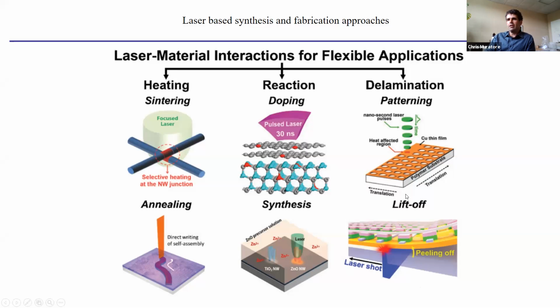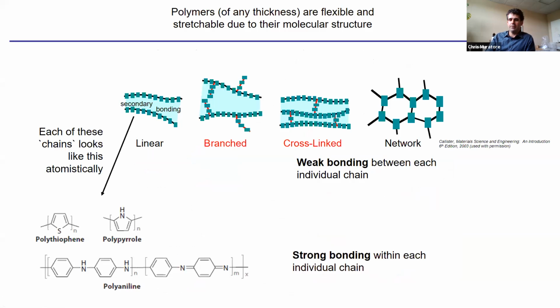Another thing you can do with a laser is lots of times you want to have transparency in an electronic device. But if you need to have an electrical contact, most conductive materials are not transparent. This is something that we just have to live with. It's dictated by the laws of physics. If it's conductive, then it's not going to be transparent. But what you can do is maintain a continuous network of a metal, which again is going to be opaque, but you could punch a bunch of holes in it with a laser, even on a polymer surface, and then it becomes transparent and conductive. So there's lots of tools that lasers enable that are useful for flexible electronic materials.